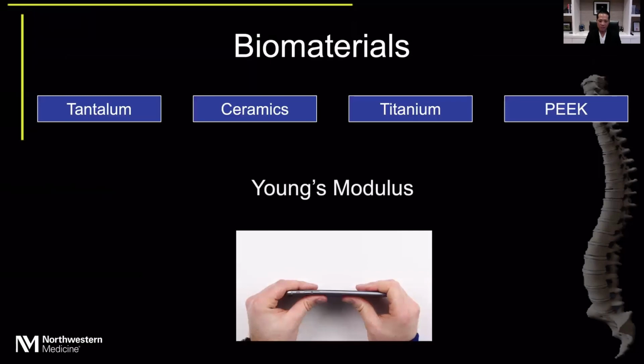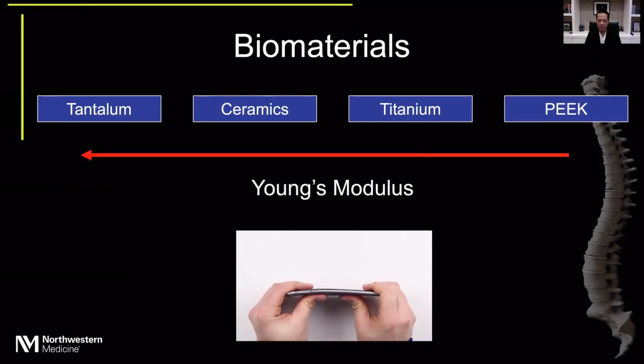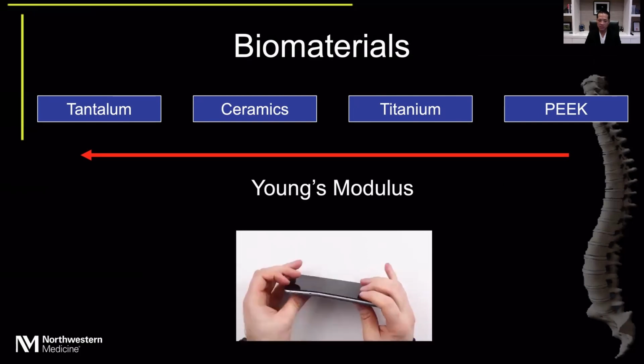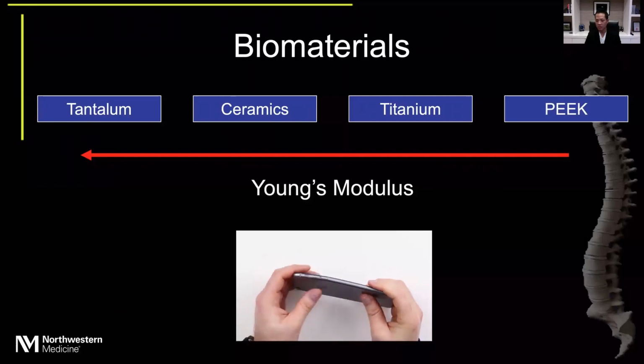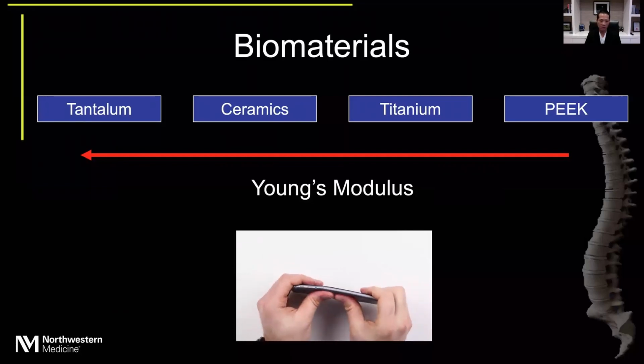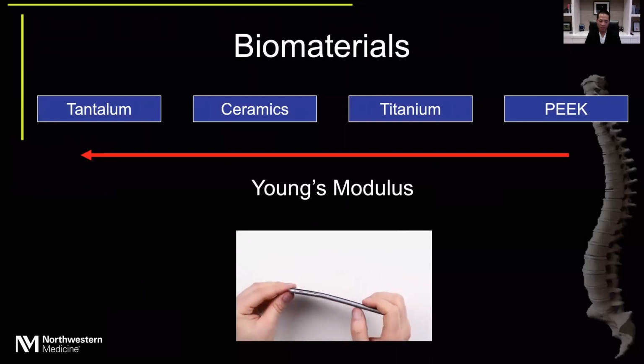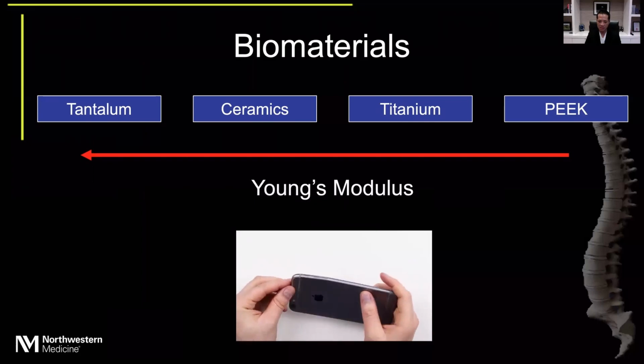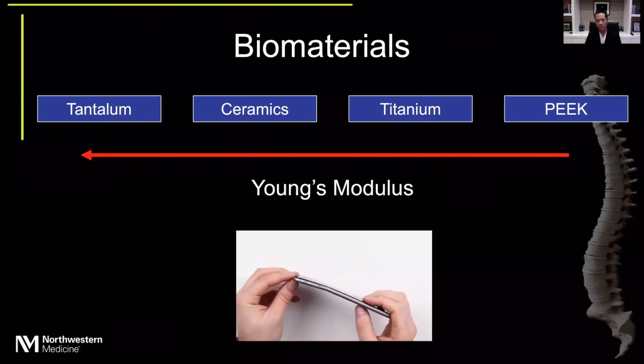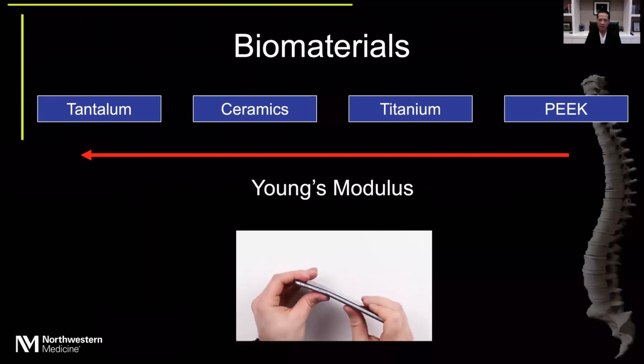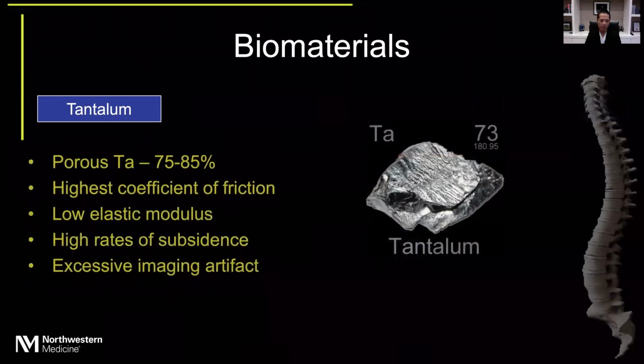One of the first characteristics of a biomaterial that a surgeon should recognize is the Young's modulus of each of the materials. On one end, PEEK is very close to bone in terms of Young's modulus, while tantalum on the other end is much stiffer. What this leads to is the possibility of subsidence, and subsidence can then lead to either non-union or collapse of the foramen after surgery.